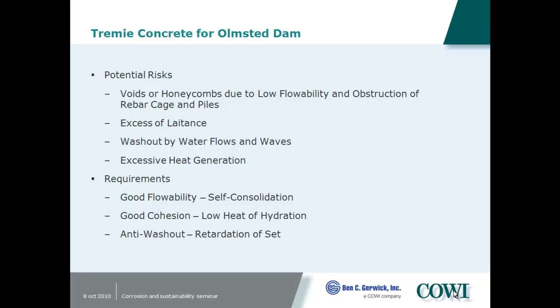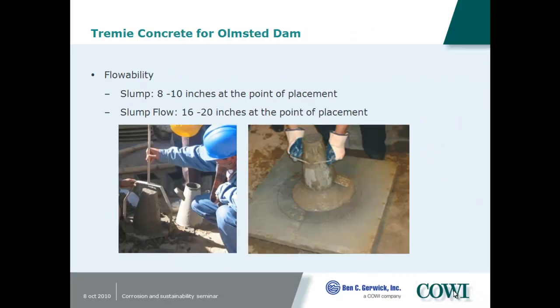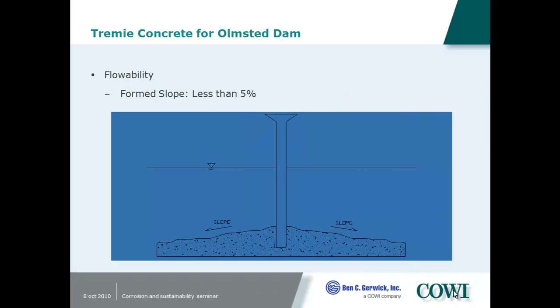We used an anti-washout admixture, which you could think of like salad dressing. It's an admixture that makes it thicker, so instead of running like water, it's more like salad dressing. So we had a 10-inch slump on the concrete for Olmsted Dam, rather than like what we used in Florida. And there's also a slump flow table test where you measure the diameter of it as it flows out, which is another measure of its consistency.